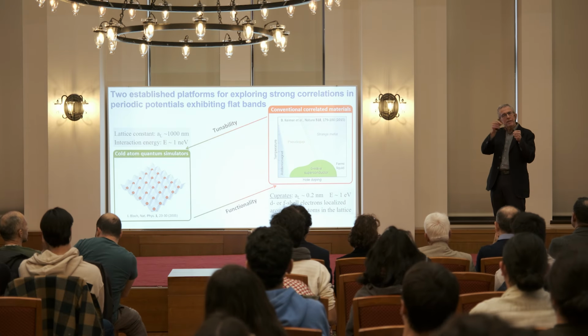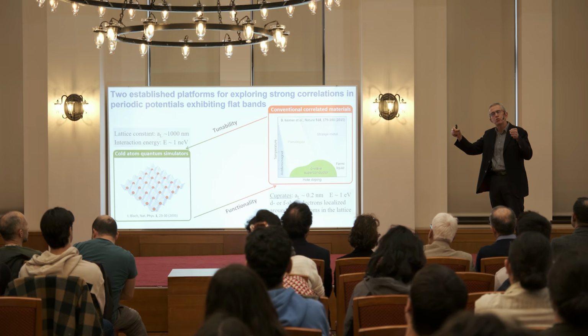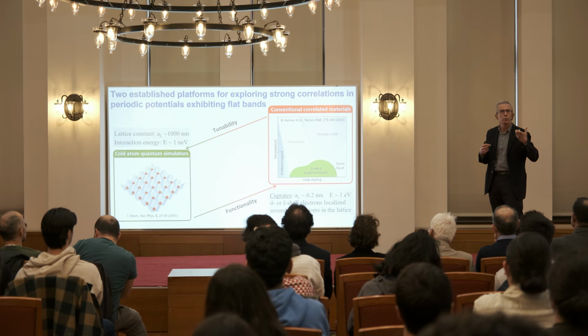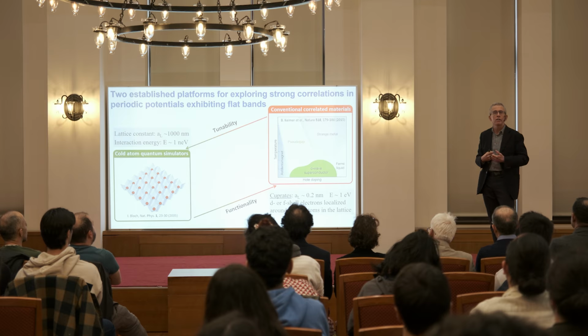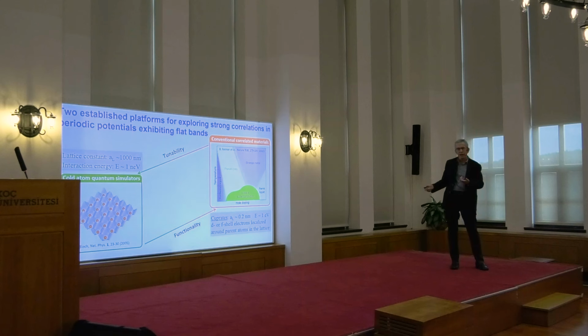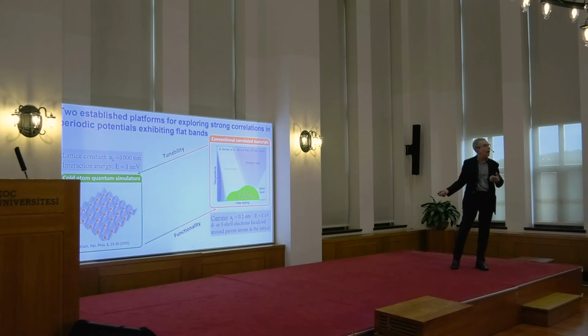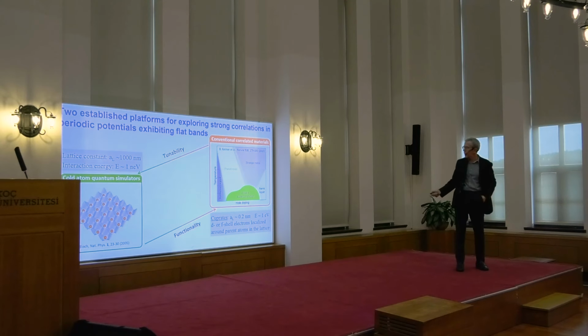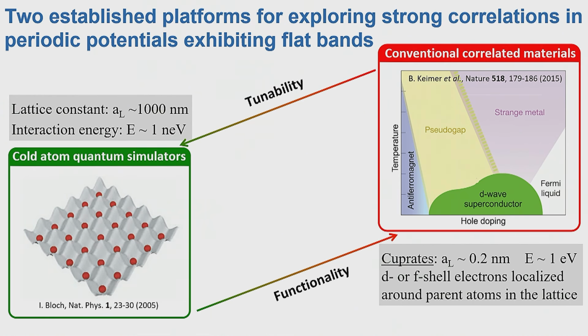Okay, so that means that their ability to move, their response to external forces, is much weaker than what you would expect, for example, for a free electron. So the effective masses in these systems can actually be very large. It can be 100 times larger than the free electron mass. And this is the phase diagram of a cuprate material. I'm not sure which one it is now, but it basically shows the phases that the community has measured as a function of temperature and as a function of the hole doping in the system. So basically you have many materials. Each one has a different dopant atom that changes the structure. Okay, so if you have no dopants, it's an insulator that is an antiferromagnet.